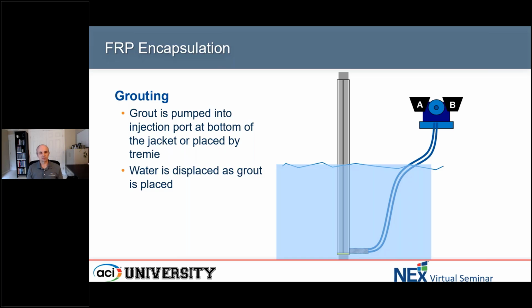So then as the grout is placed into the annulus, the grouts are designed to have enough density to displace any water that's entrapped between the FRP form and the existing structure. As the grout is placed, it's placed from the bottom of the encapsulation, working its way up. And as it's placed in the bottom, it forces water to rise to the top of the encapsulation, and then eventually that water is expunged out the top of the encapsulation as that grout is placed in.